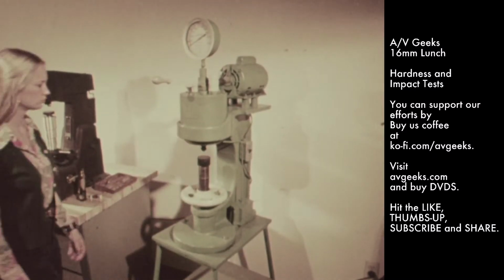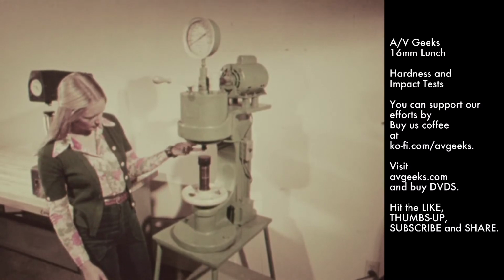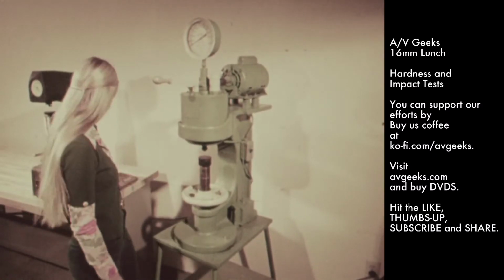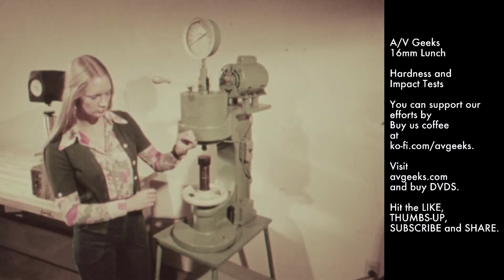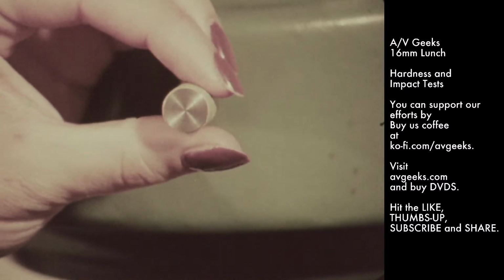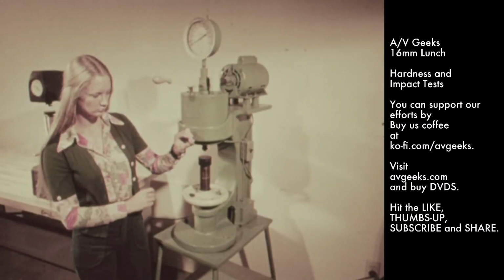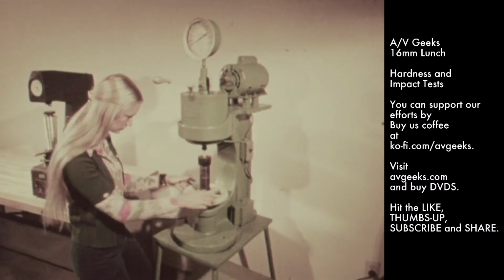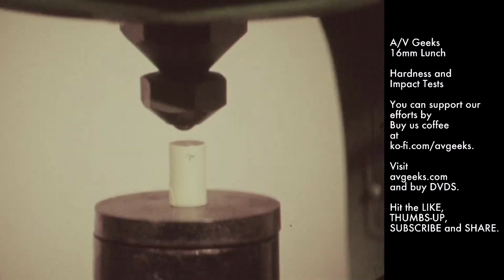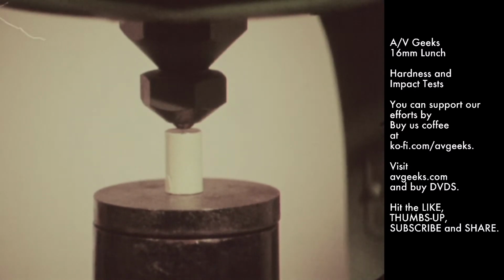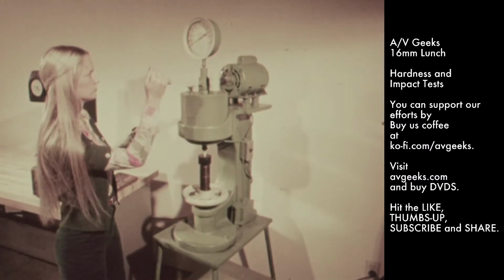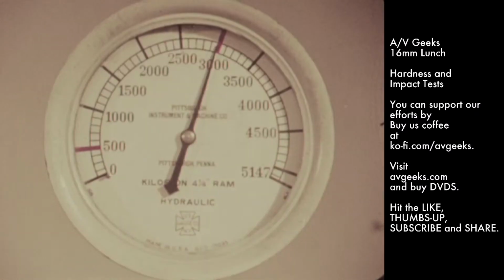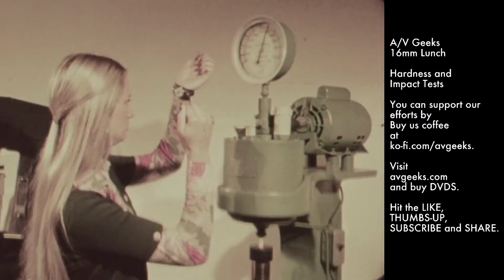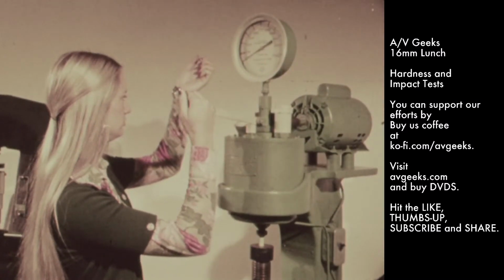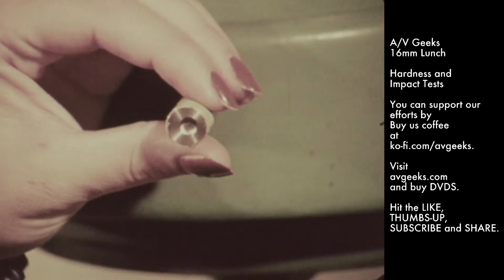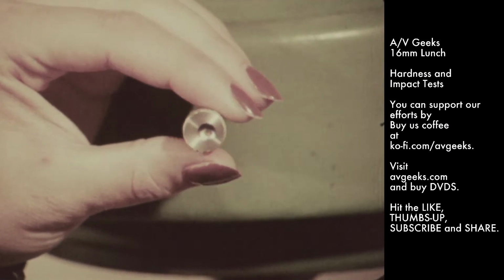Two common tests for quantitatively evaluating resistance to penetration will be examined next. The Brinell hardness tester uses a specified load to force part of the lower surface of the 10 millimeter diameter hardened steel ball into the test material. The penetrator is brought into contact with the specimen. The load is applied hydraulically, held for 30 seconds, and then released. A spherical indentation results.